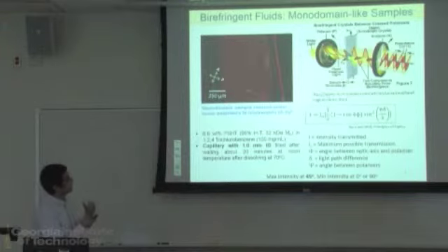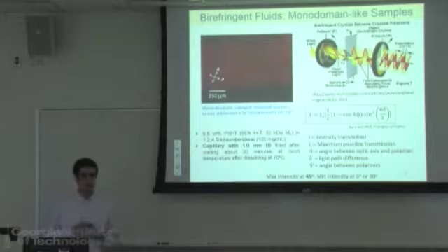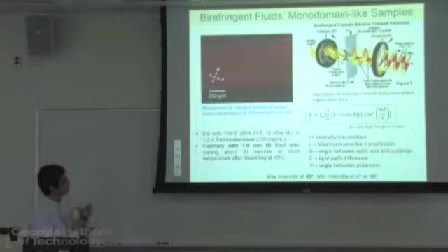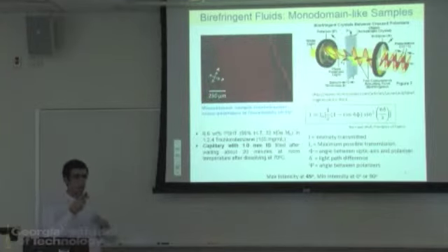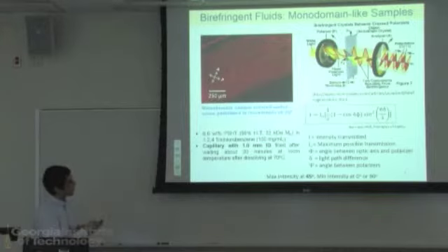And you can see here, what we did with P3HT solutions was increase the concentration to very high, 6.6 weight percent. That's about 100 milligrams per mL, which is the most you can get out of this particular P3HT, and this is in trichlorobenzene. What you can see is as you fill a capillary tube with this solution and rotate it between these polarizers, there's a repeating pattern of completely dark and then completely bright as you rotate. When it's completely aligned with the polarizer, it's dark. When it's at 45 degrees, it's brightest. This indicates that there's definitely some long-range ordering in this solution.